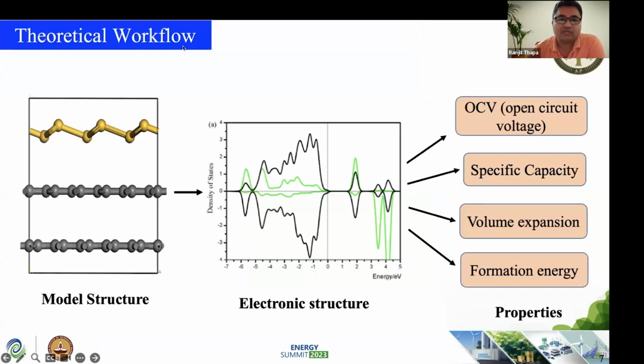So what theoretical workflow do we follow? We consider different model structures, and then we calculate the density of states, band structure and different parameters. Then, using our total energy, we calculate open circuit voltage, and we can calculate the specific capacity, which is a theoretical specific capacity. We calculate volume expansion and we calculate formation energy. This is what we can do with density functional theory in our group.